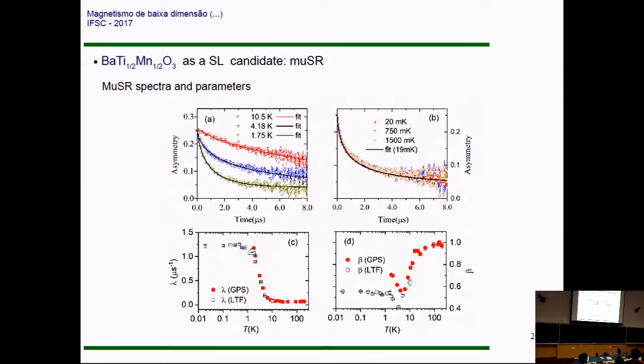And what you see is that if I simply measure the relaxation rate, it is pretty much constant at high T, and then it goes through a really steep increase and flattens again. And this region here is precisely the same region where you observe the bump in heat capacity. So I think this illustrates quite nicely the relation between macroscopic and microscopic measurements. So something is going on here, and we believe this is exactly a crossover, as we said.